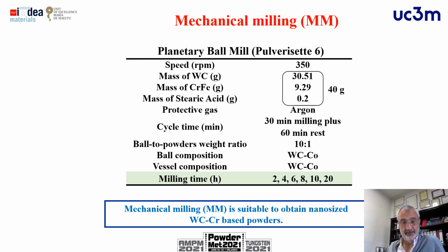These are the mechanical milling conditions that we have used. The ball to powders ratio is 10:1, and here we have the amount of tungsten carbide and iron chromium that we have used. We have used stearic acid as a process control agent, and we have also used argon in order to avoid oxidation. We have tested different milling times.